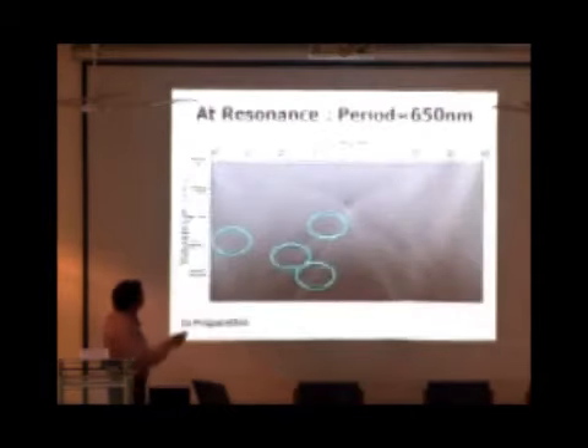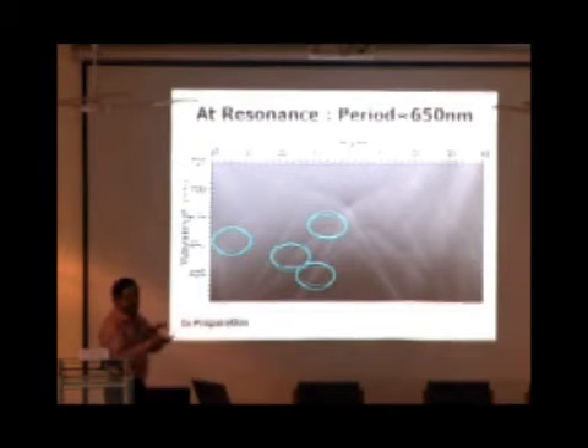So when we make the period of the top grating, we are essentially making this localized plasmon mode and the surface plasmon mode resonant. When we have the resonant condition, each of the propagating plasmon modes interacts and couples to the localized plasmon mode, and you see splittings in your energy levels, and the dispersion becomes pretty complicated.